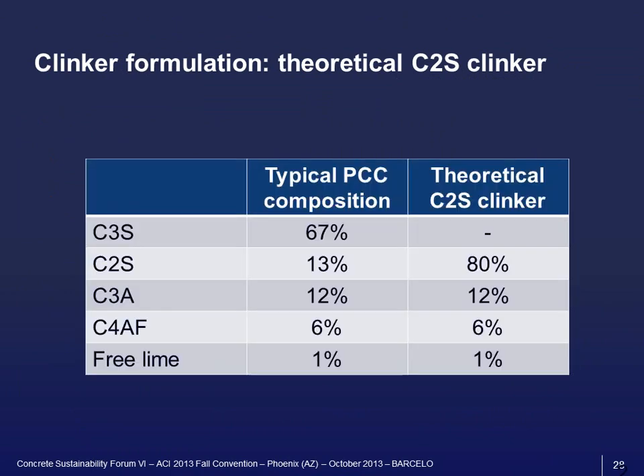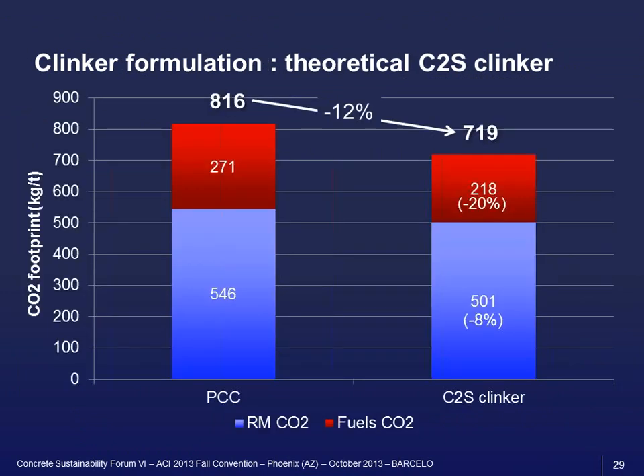So we can wonder, okay, why not? Why won't we go through C2S type of clinker? And why not eliminate C3S and make a clinker which is only C2S and C3A and C4AF, because we need a little bit of liquid phase in the kiln for the clinkering reaction. But why not go there? If we would go there, the CO2 footprint of the cement would be reduced by 12%. And you can see, we would go from 816 to 719, and the bulk of the reduction would come from the fuels, and indeed we would have a minute reduction of the CO2 from the raw materials.